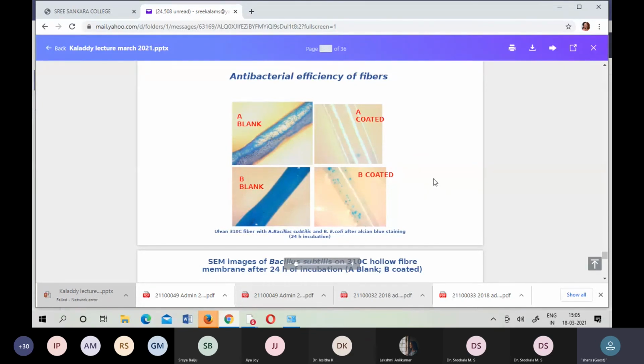So instead of going for the chemical method, people are using chemically coated or nanoparticle membranes. Even I did it. We do some nanoparticle coating on the membrane surface, or some polymer brushes, or changing the thickness or some parameters, or a physical treatment. Somebody does gamma treatment, laser treatment, many treatments we do. We make sure we are getting a less fouled membrane. Whereas here, with very minimal concentration of the chitosan, we were able to say, yes, we can control the membrane fouling to a certain extent with a limited coating of chitosan.